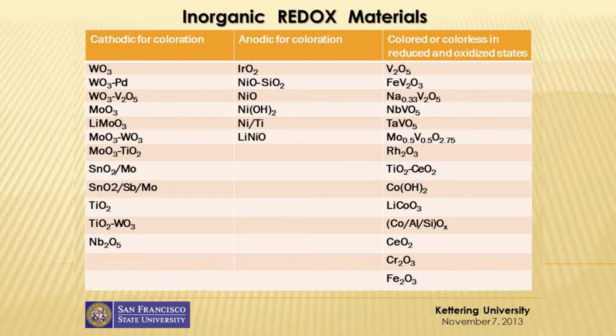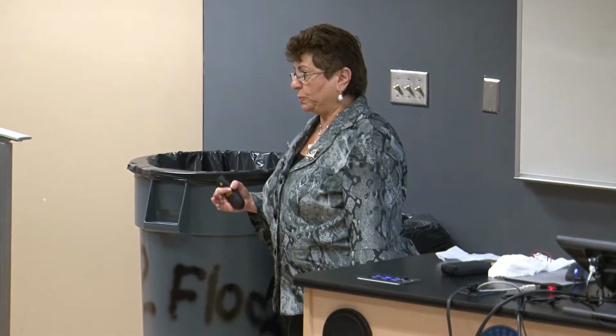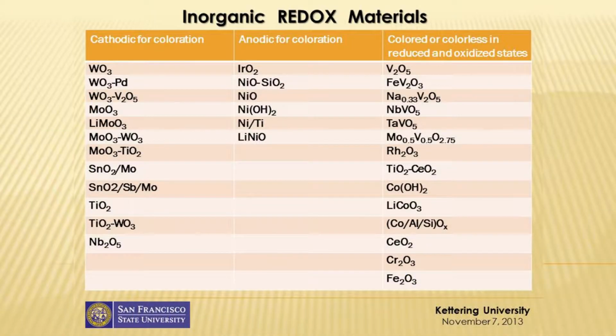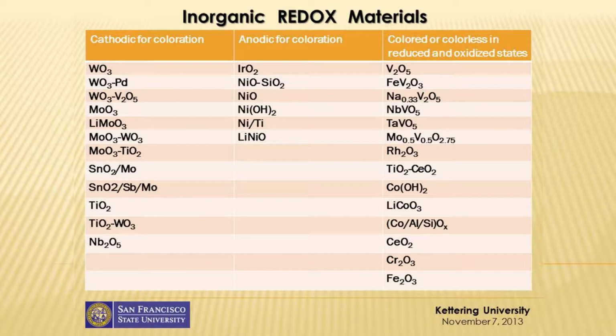Cathodic materials color when they are reduced. Anodic materials color when they are oxidized. Typical examples of those materials are iridium oxide, nickel oxide, silicon oxide, nickel hydroxide, and so on. There are some materials that are colored or colorless in the reduced or oxidized states. Those are vanadium pentoxide, iron vanadium oxide, sodium vanadium pentoxide, niobium vanadium pentoxide, and so on.